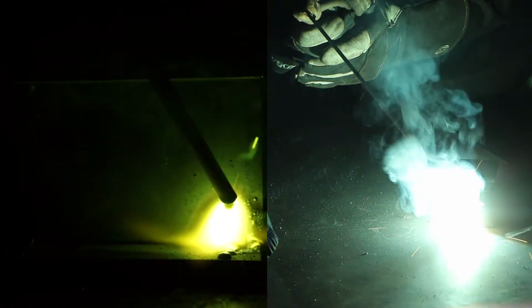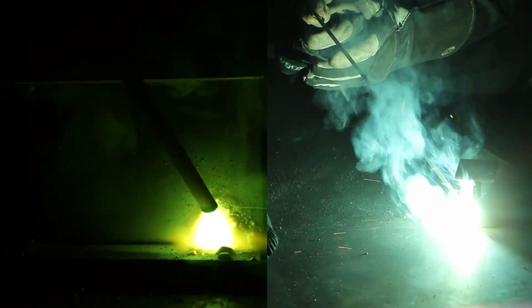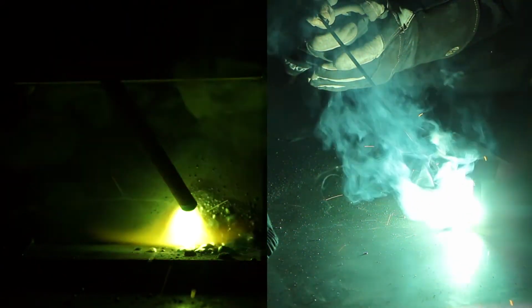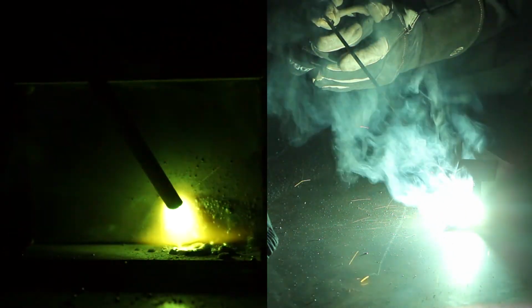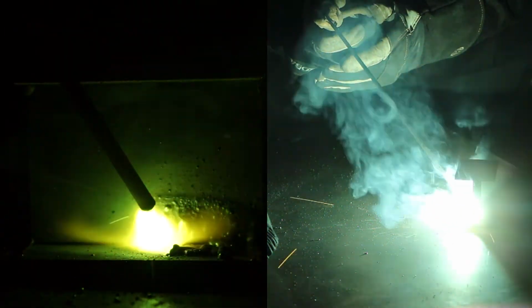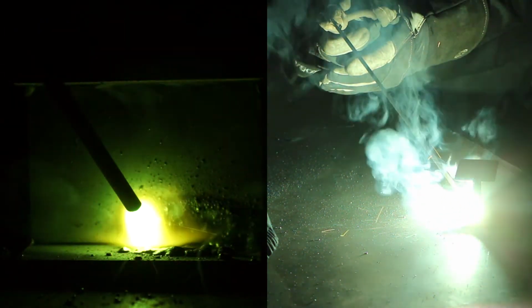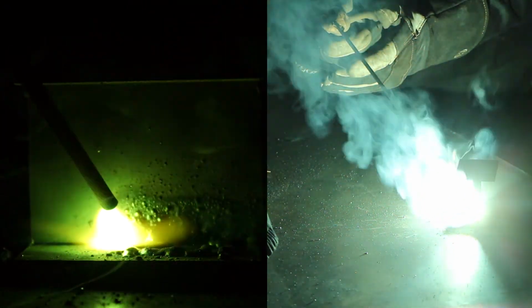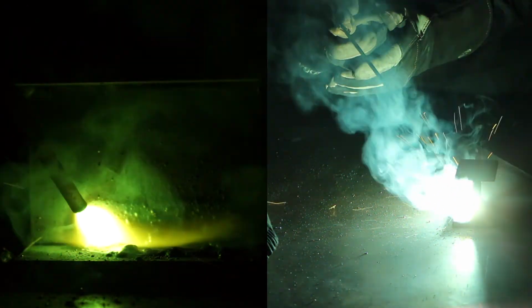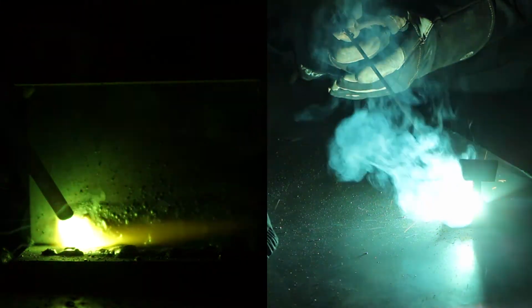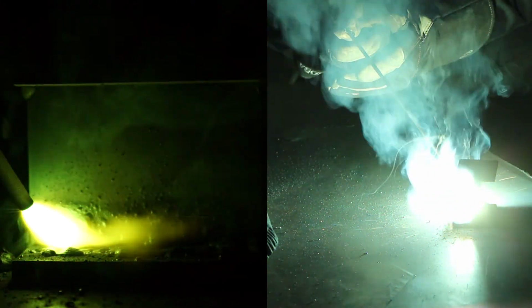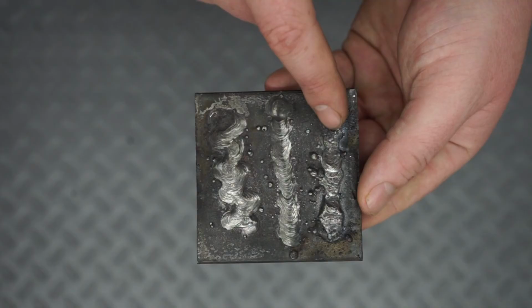First, let's observe long arcing. From this view, we can see our puddle, and we can see an overview of how the rods are being manipulated. You can see here that the arc length is incredibly great, and instead of seeing a concentric puddle form, we see what appears to just be flame coming out of the tip of the electrode. Also, if you notice on the right side, an immense amount of light is generated from a long arc. Long arcs tend to show little or no puddle formation, and they leave a large amount of spatter.